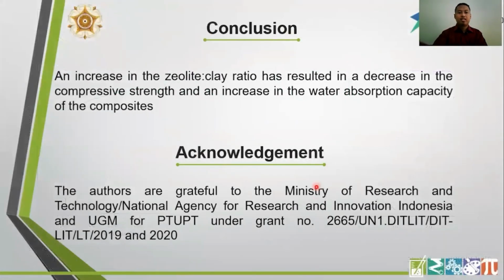Ladies and gentlemen, as a conclusion, we conclude that an increase in the zeolite to clay ratio has resulted in a decrease in the compressive strength and also an increase in the water absorption capacity of the composite.